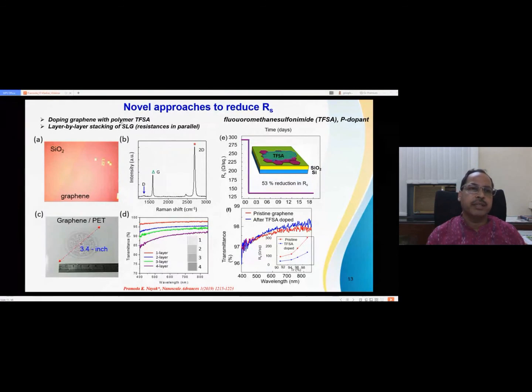First is by doping the graphene with a polymer like TFSA. This is a famous polymer which is doped in carbon nanotube, and mostly Professor Ali Javed's group works on TFSA doped graphene or TFSA doped TMD. When you do TFSA, it is just like a p dopant, and it will p-dope the graphene. The Fermi level goes below the valence band maximum. So there is a reduction in the resistance. With TFSA doped graphene, we are getting 53% reduction in the resistance.